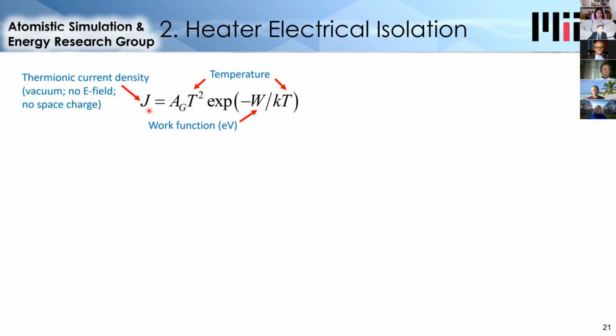And one key equation to look at is called Richardson's law. This shows that the thermionic current density, which can be thought of as like the current, like the amperage flowing out of the heater through the gas, is equal to the temperature squared times the exponential of the work function and also related to the temperature. So you see the two key variables here are the work function of the material, which you would want to be high to avoid arcing, and the temperature, which you would want to be low to avoid arcing. However, the temperature is fixed in this case, and the work function of the two candidate heater materials, tungsten and graphite, are very similar, around 5 electron volts.